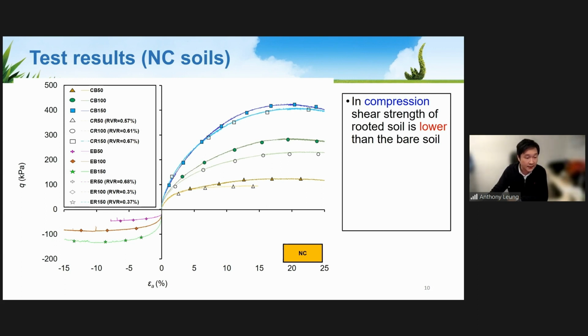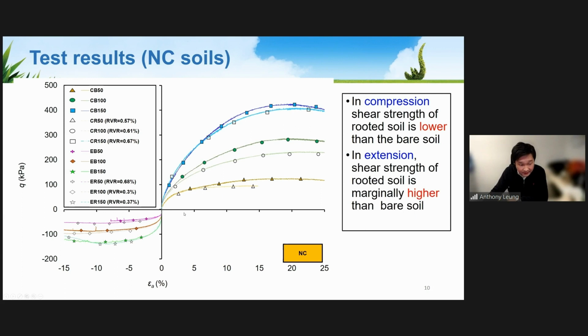So along the extension, this is the result you can see for the bare soil. And if I again superimpose the result from the rooted soil case, you see apparently a very small increase in shear strength. Now, although visually it looks like a small increase, if you focus and enlarge the scale here, the increase actually is quite a lot along extension.